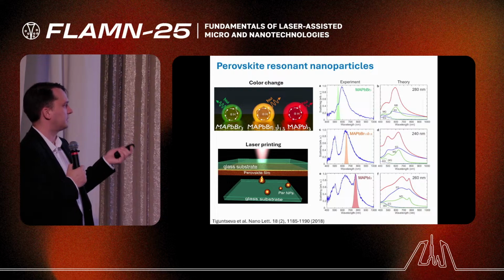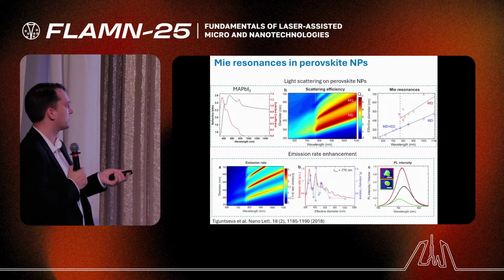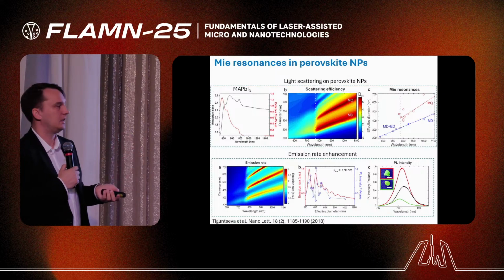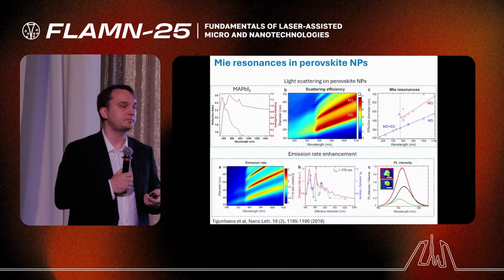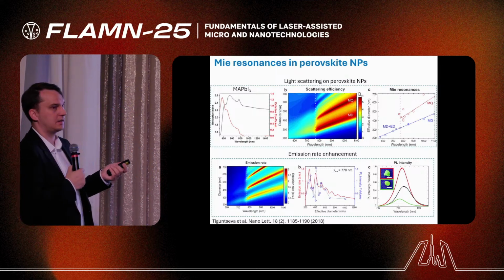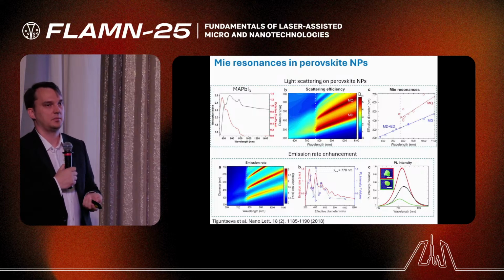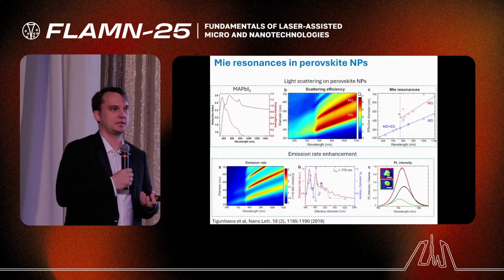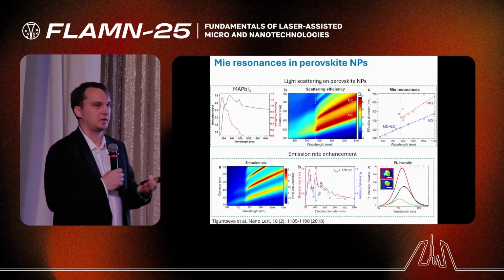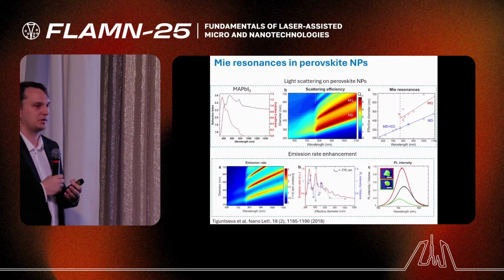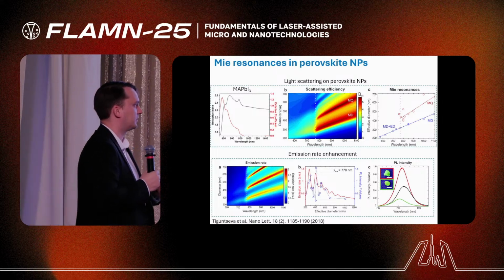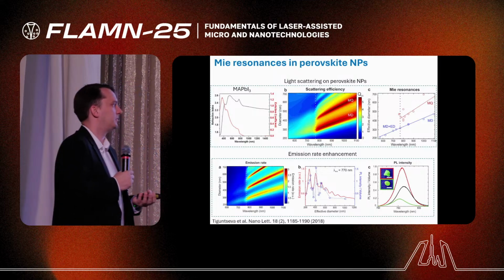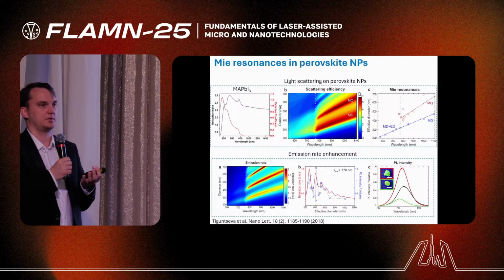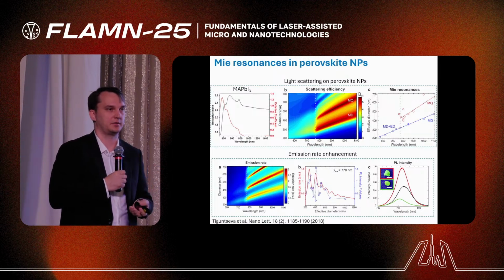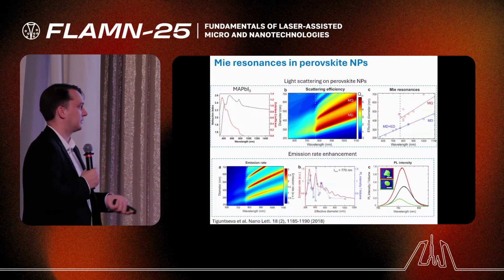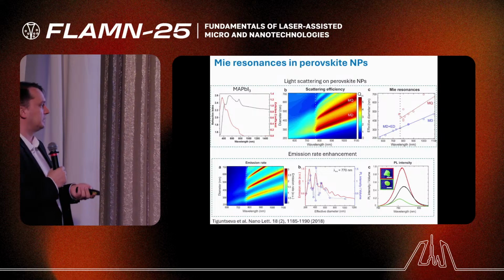And also again we have resonant properties for such nanoparticles. We printed different nanoparticles, calculated their scattering efficiency, and also studied their emission properties. Emission is even enhanced because we still have photoluminescence, and also we have a cavity. Like Professor Kavokin also told us, cavity is important for polaritonic effects. Here, the cavity is important to couple, in the weak coupling regime, our emission with the shape of the particle. Each particle is like a self-resonating system which emits light, and this light couples with the material and resonates.